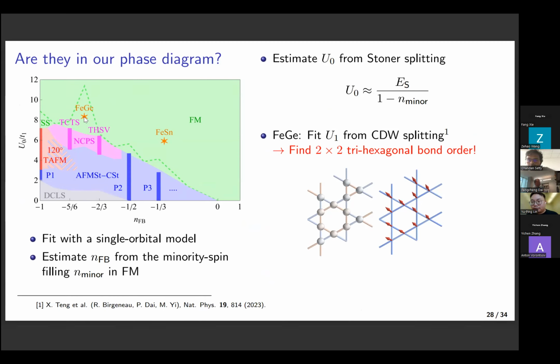I see. Yeah. So I just want to point out that we studied this in the case of both the vanadium and the iron germanium, and we also find this kind of order which mixes the charge and the spin, and depending on the filling, you can get striped orders, which is similar to what they found in experiment. But the key point is that in our work, in order to obtain this mixing of spin and charge, you need to consider the non-trivial topology of the bands, and that seems to be key. That's a very important point. I'm wondering whether in your work you take into consideration any topological aspects of the band, or you just treat the whole thing without spin coupling.